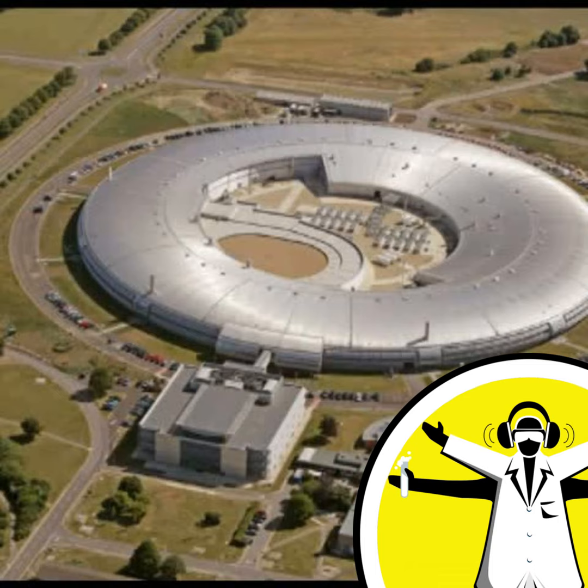So how do you actually then set about recreating these conditions and actually looking at the reactions of green rust here at the synchrotron? Well, what we've done is we've developed a reaction cell which can mimic the conditions of green rust formation within, say, a soil or potentially in a contaminated land site, to mimic the pH, the acidity, or the alkaline nature of the solution, and also the redox potential, so how oxidizing or reducing the environment is. And that's really controlled by the amount of oxygen that's present in the system. And by doing this, we can synthesize and form the green rust, but also by flowing the solution where we're forming the green rust through the synchrotron beam, through a capillary which is mounted on the synchrotron beam, we can characterize the formation reaction and the process by which the molecular structure of green rust is built.